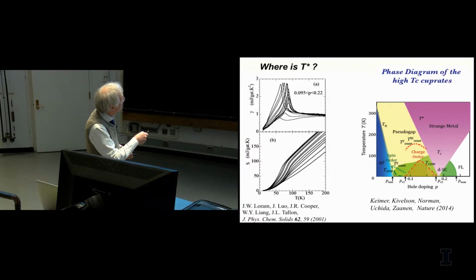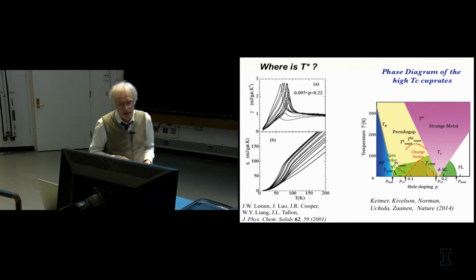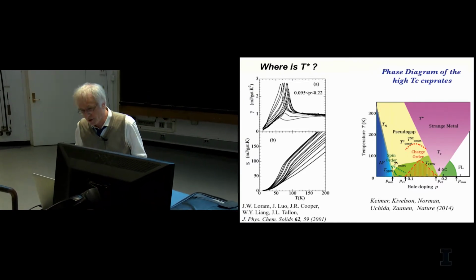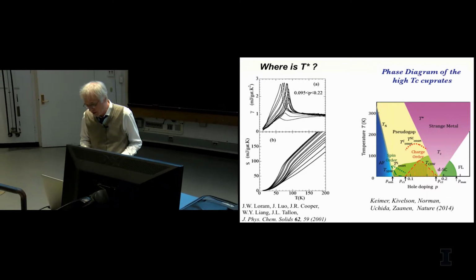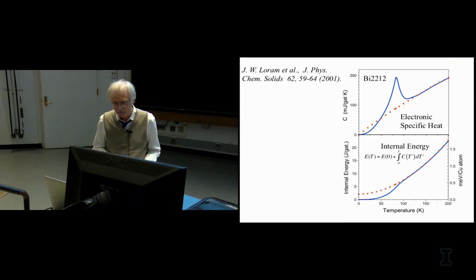Now, what you would expect if the pseudogap would close is that those curves would come back to some straight line that does extrapolate to 0, but it actually never happens. And that's a very strange thing. You don't actually see in these thermodynamic measurements an indication of a pseudogap closing temperature.